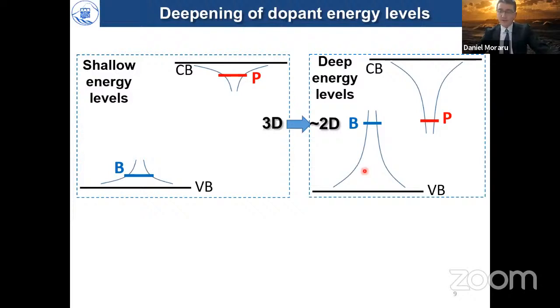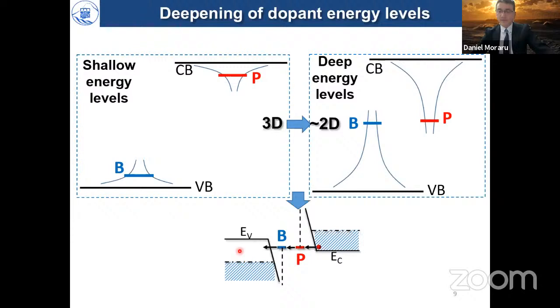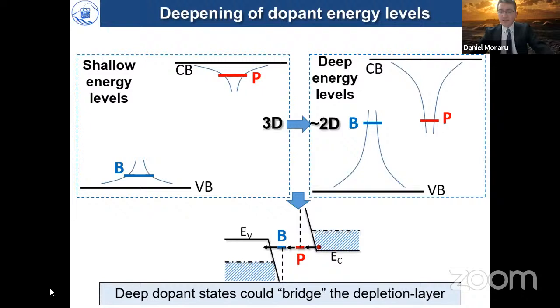If you also include the fact that we have a built-in potential, then you can imagine that we have a possibility to align boron states with phosphorus states, boron on the P side and phosphorus on the N side, and thus create a favorable path for the electrons to move between the bands. So this is what we'd like to identify, and this is what we propose as an interpretation for the results that we observed: the fact that deep dopant states could in fact bridge the depletion layer and create these enhanced current peaks.